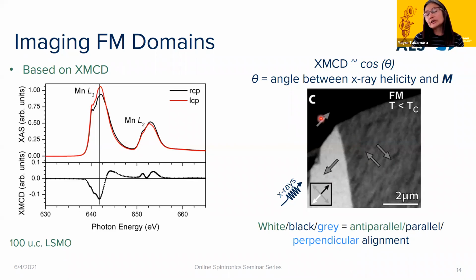And so what you can see for LSMO is that in general we have very large magnetic domains. Again, it's somewhat dependent on the thickness of the film, but they are many microns in size for an unpatterned film.